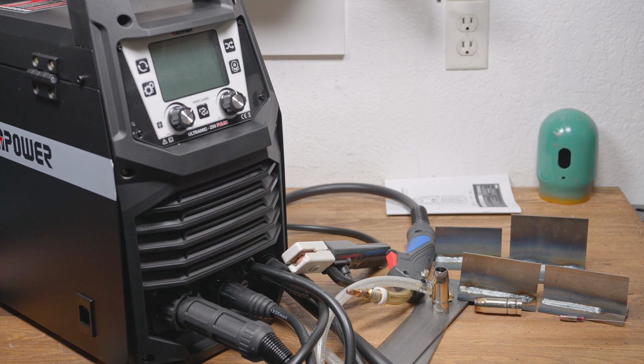Still, pulse probably isn't the best mode for beginners. If you push this machine very hard, it turns out you'll burn up the included MIG gun long before the cheap cables or work clamp overheat. The included MIG gun is just not up to the task of high amperage pulse welding. I keep saying it, but pulse is a spray process, which is really hot. When maxed out after running just a 3 to 4 inch bead, the nozzle on the MIG gun was basically on fire.